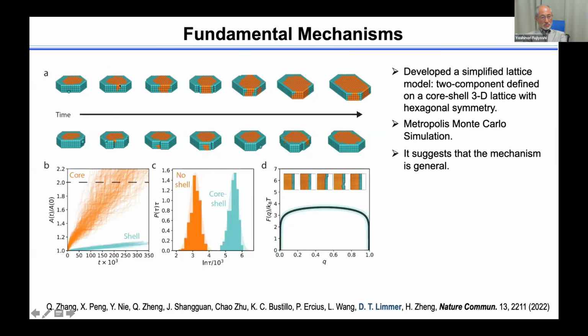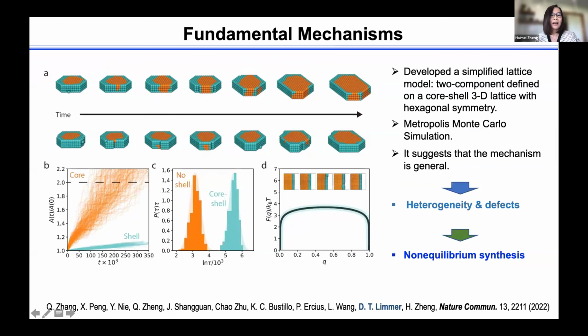This core shell allows this system to fluctuate in response to the chemical potential. And it shows remarkably similar behavior to what we observed when there is a crack developed in the shell, and then this core can grow very fast. However, it can stop growing when this crack is healed.